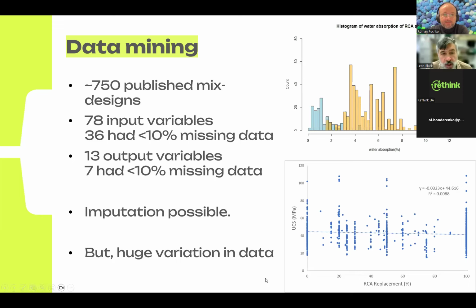Of these 78, 36 of them had less than 10% missing data. Okay? And that's important because the smaller the percentage of missing data, the better that we can impute. So we can use mathematical formulas to fill in the missing data. We also identified 13 output variables. So these 36 input variables and the imputation. This is shown, for example, on the right-hand side.